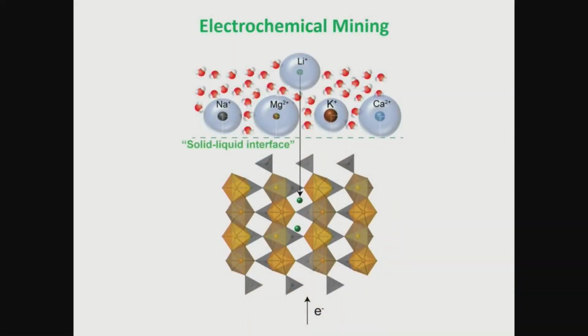Lithium has the advantage because it has only monovalent charge, less charge than the other types of ions, and it's very small in its ionic diameter. So in that sense, when lithium travels through a solid, it's much faster than the other types of ions. That's a huge advantage to achieve lithium selectivity. And this is the core part of our innovation. But at some very dilute concentrations, sodium will start to compete again with the lithium because they just look very similar. They are like cousins, and they want to sit in the same structure.